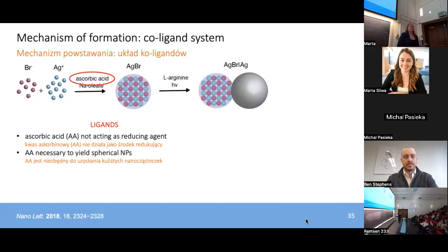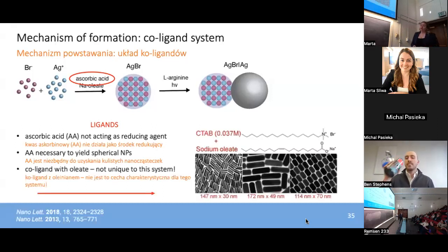So if we simply eliminate ascorbic acid out of our synthesis, we don't get spherical silver bromide, we get these silver bromide dendrite antler-like species. They're highly susceptible to reduction in the electron beam or under the transmission electron microscope beam, which indicates to us that there's just not enough stabilization occurring there without the ascorbic acid. So we know ascorbic acid is not a reducing agent, and it's necessary to yield spherical silver bromide particles. So we hypothesize that it's acting as a co-ligand with the oleate to form the stabilizing ligand shell.